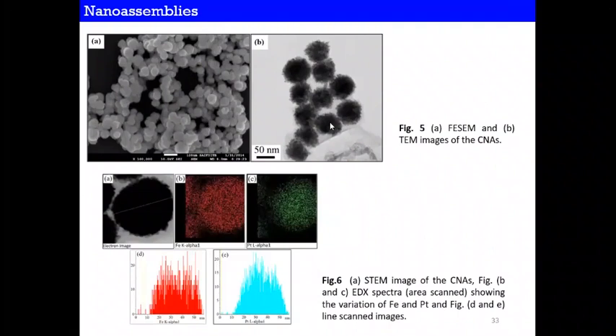So small particles can aggregate and form the cell assembly, and it has been coated with PEG diacid, polyethylene glycol with carboxylic groups. One carboxylic group is attached to the iron, and another carboxyl group is free, followed by the PEG. So it gives very good colloidal stability.